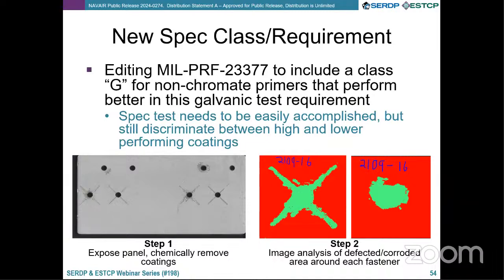Likewise, we've also gone in and done volumetric analysis and found that an areal extrapolation is good enough to discriminate products against each other. But what I was hoping is we could say, here's a line, and this is the amount of area that can be undamaged to still pass the specification test. But variations in coupon quality, in terms of the metal itself, the pre-treatment corrosion resistance, as well as thickness of the primer and so on, have made setting that chalk line very difficult.